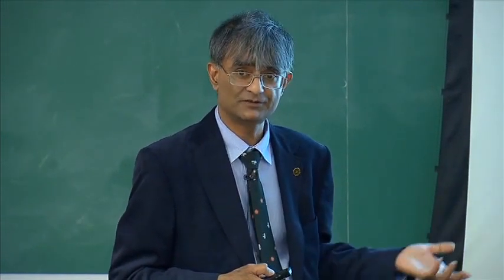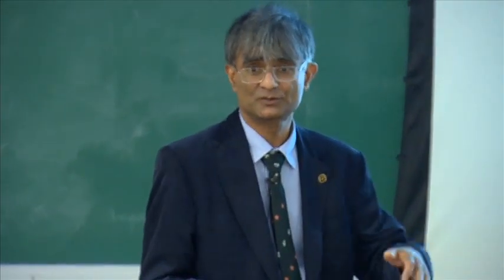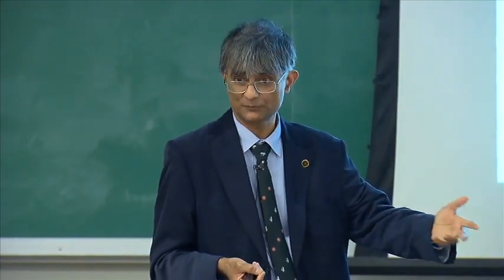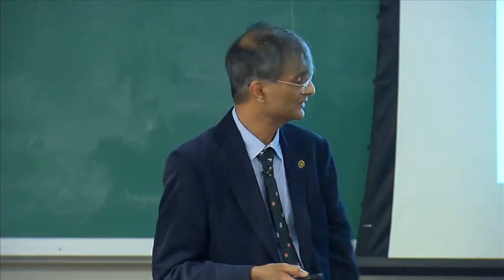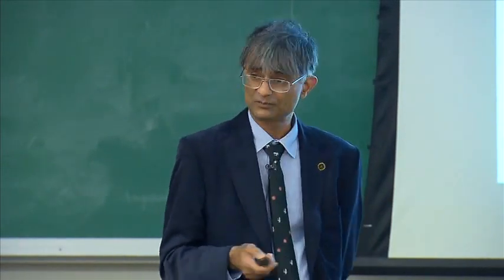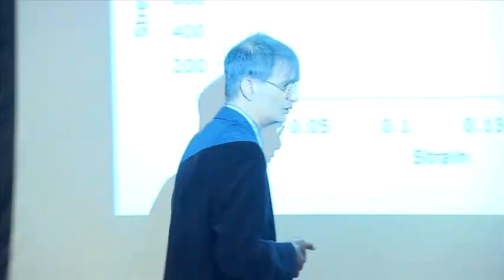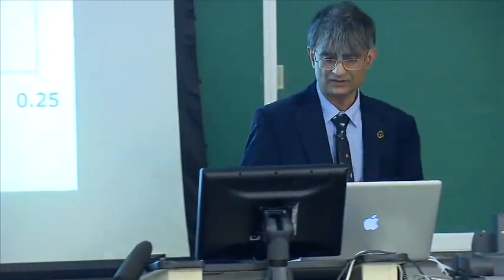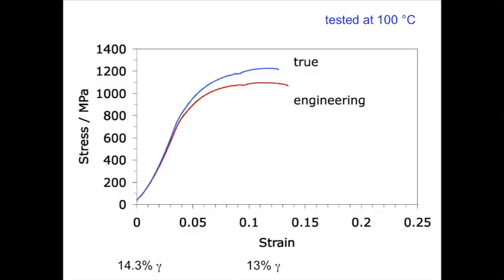tensile test at 100 degrees centigrade. Now 100 degrees centigrade doesn't do anything to the microstructure because it's produced by transformation at about 400 degrees centigrade to bainite. Yeah? But it alters the stability of the austenite to martensitic transformation. The austenite becomes more stable. So if the austenite doesn't transform, we should get a lower elongation, and that's exactly what happens. So here is the test done at 100 degrees centigrade, and you can see the austenite is not actually transforming. Yeah, so it's the transformation of the austenite that gives us the elongation.